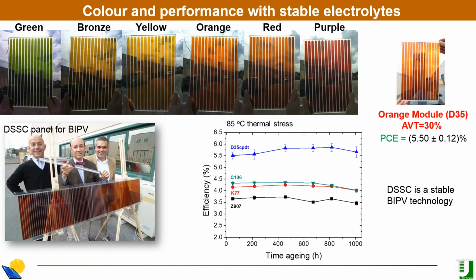The technology is quite rugged, robust. I mean, they can indeed sustain the IEC norm tests. This, for example, is 85-degree thermal stress. It's not damp heat, but you can do also the damp heat test. And then you see you can keep the efficiency quite constant, even for 1,000 hours of stress. So even though the basis of the technology is molecular, you can indeed stabilize this technology without a problem. Of course, stabilization of the technology came after a big industrial effort made by more or less 20 people for 5 years. So it does not come for free, but it is doable.